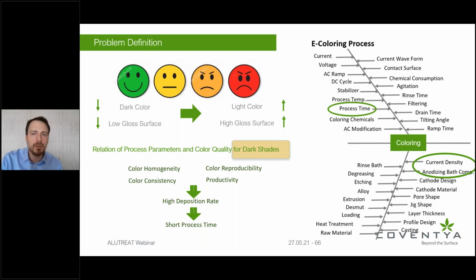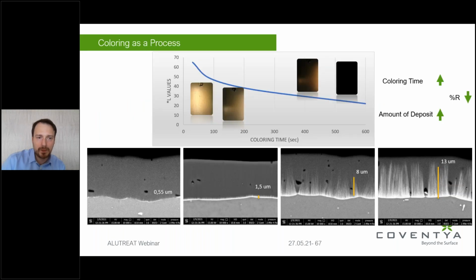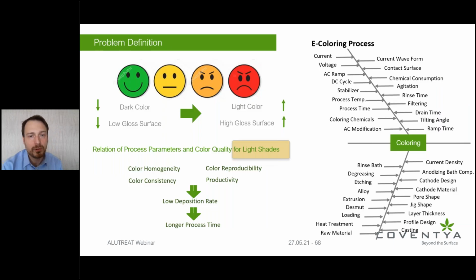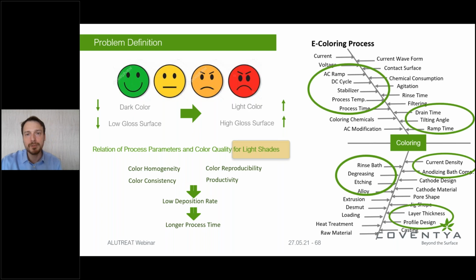So it is fairly easier as long as you are adjusting the other two prerequisites or the precursors, which is pre-treatment and the anodic cycle correctly. Then you can end up with a happier team as long as you're making a dark color and a lower surface gloss. But as we have briefly discussed, because we have a very small amount of precipitate, that means we have a very narrow margin of error. Therefore, for light shades, we need to do something else because there are other players involved in this or affecting our performance, making our life harder.